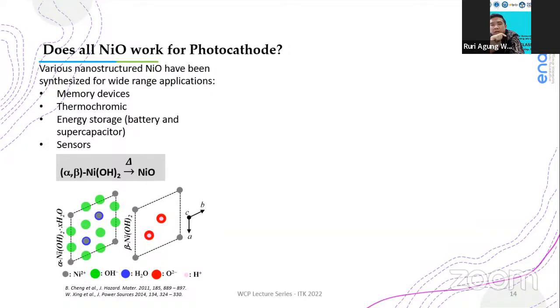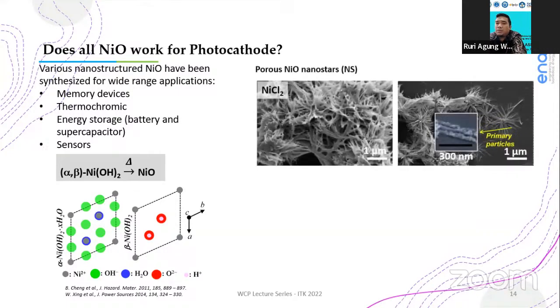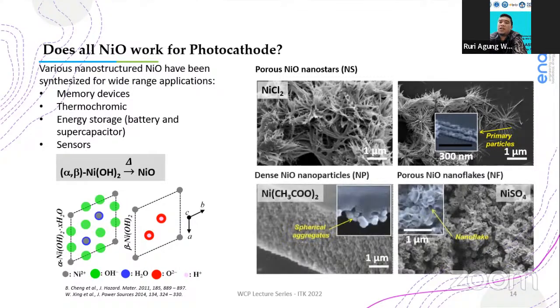Here we should note again that nickel hydroxide has different polymorphs. Mainly there is alpha, beta, and gamma, but mainly the alpha and beta phases are discussed here, where alpha nickel hydroxide contains water molecules within the interslab spacing, while beta nickel hydroxide contains water molecules only on its surface. In this case, we prepared mesoporous nickel oxide nanostars. Here we got nanostars using nickel chloride precursors as a benchmark structure, but we also prepared dense nickel oxide nanoparticles from nickel acetate and also porous nickel oxide nanoflakes from nickel sulfate.